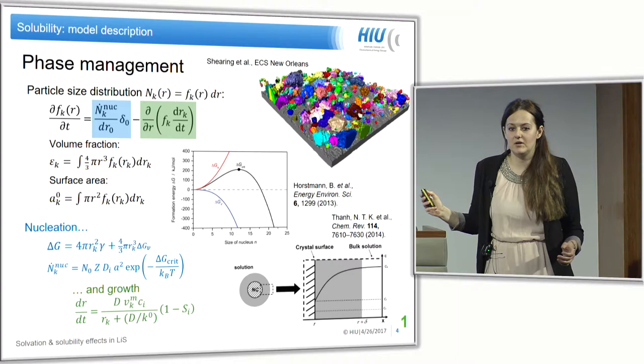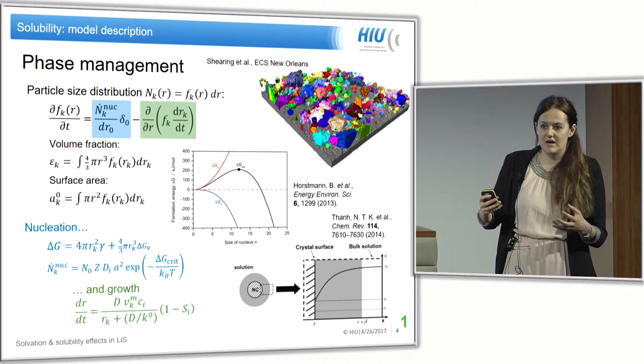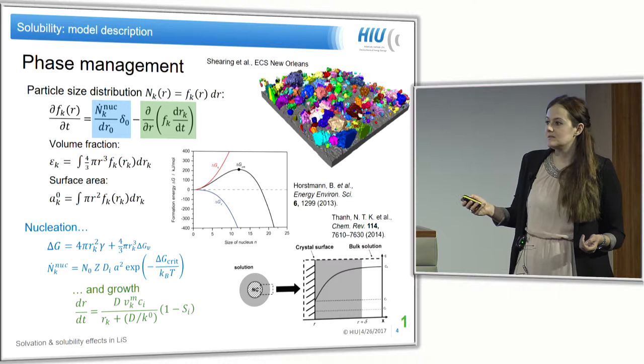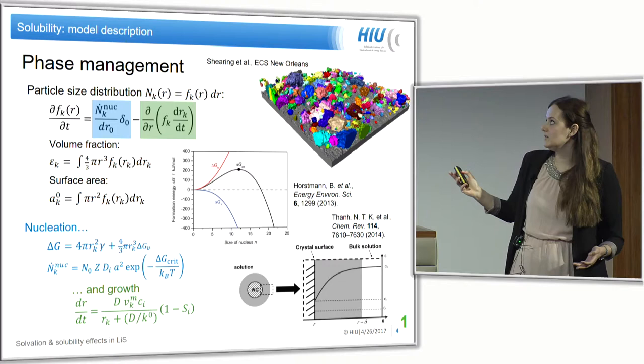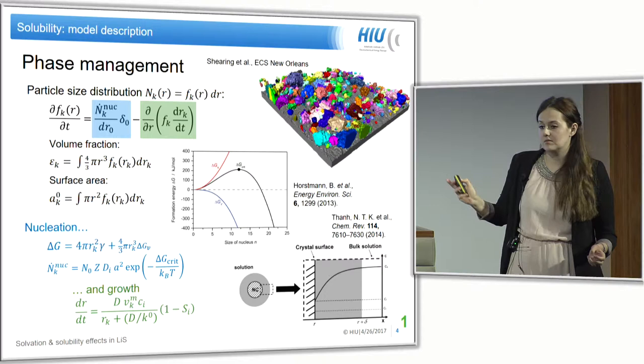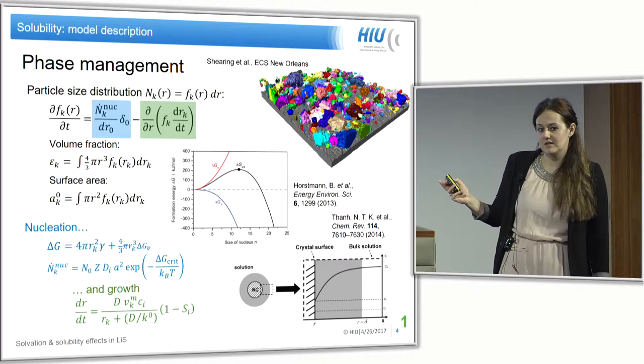The aim of this work was motivated by in-operando tomography data from Paul Scherrer Institute, visited us in Ulm, showing sulfur particles shrinking, growing, and redistributing in the cell depending on their size and distribution. We thought it would be nice to model this. In addition to the microscopic cell model, we also calculate the particle size distribution N, or its probability density F. We calculate the covered surface and corresponding volume fraction from the integral over the probability density, assuming spherical particles for S8 and hemispherical particles for Li2S.